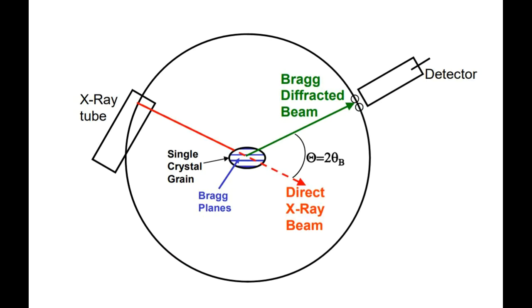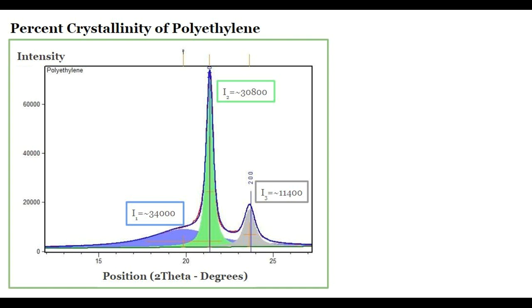There are several methods for determining the degree of crystallinity in a polymer. X-ray diffraction can be used to determine degree of crystallinity because intensity of X-ray diffraction reflection is proportional to the material density. An X-ray diffraction pattern displays both sharp Bragg's peaks arising from the crystalline portion and a broad diffraction peak caused by scattering from the amorphous portion of the polymer.